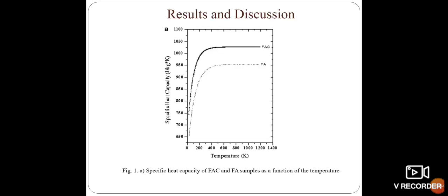Next are the results and the graph which shows the temperature versus specific heat capacity for the FA and FAC samples. From this, the temperature dependence of the specific heat capacity is in line with the typical behavior of solid materials. At low temperatures, it can be observed the tendency to the T3 law behavior. For high temperatures, the specific heat increases rapidly to the constant high temperature limit predicted for polyatomic solids. The specific heat capacity values of FAC samples are higher than the values of FA samples due to the presence of high content of Fe2O3.